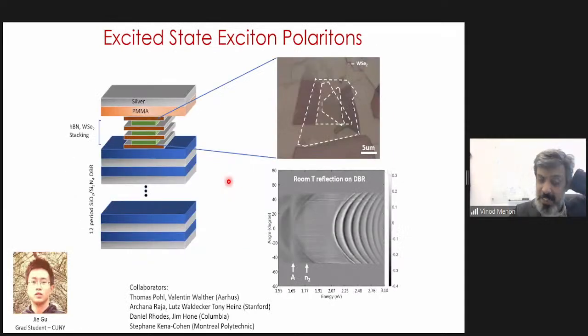And what one sees is that, so this is the structure. This was done by my then graduate student Jay, who's soon going to become a faculty. And he took 3 layers of this 2D material, sandwiched between boron nitride layers, put it between 2 mirrors. I'm making it sound trivial. Making a device like this is not that trivial, especially when you have 3 layers and so on. But thanks to Jay's dedication and drive, we were able to get that. We also had a bunch of collaborators on this work. Theory was primarily led by Thomas Pohl's group, the group of Tony Heinz for some spectroscopy, and the materials were provided by Jim Hone's group and Stefan Kena-Cohen for some of the theory insights as well.